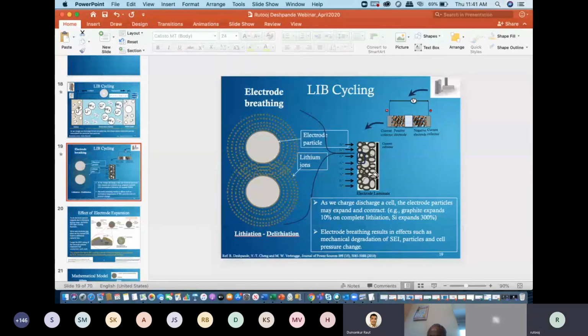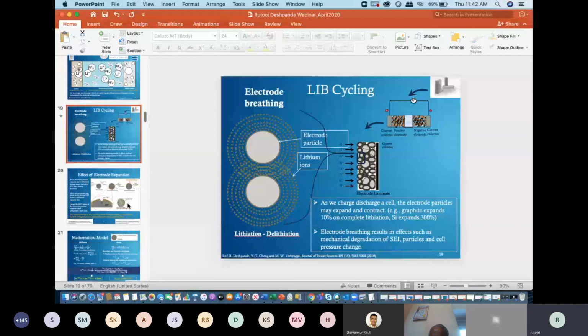Yeah, there are a large number of additives available, for example, vinylene carbonate or FEC. But again, the additives of each company are the secret recipe. So why, let's say, would a Panasonic cell work better than some random cell supplier? I don't know if it does or not, but if it works better, that's because they have a better recipe of additives. They can put the right additives, which can form a good SEI layer. And now this SEI layer is more passivating. It doesn't mechanically deteriorate as much, and then you can get much better cycle life.